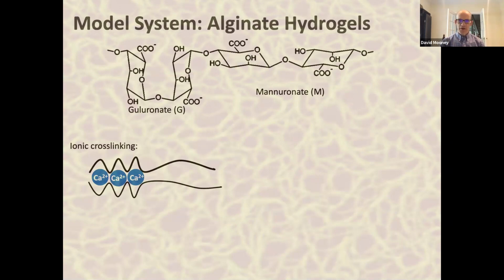Now, to explore this, the model system that I'll use in most of the data that I'll present today are hydrogels that are formed from a polysaccharide called alginate that is typically derived from seaweed. This is a block copolymer comprised of 2 different sugar units that are arranged in blocks. And for simplicity today, I'll just refer to the G blocks or the M blocks. Now, the relevance of this block structure is first that these polymers can cooperatively share divalent cations such as calcium to form a space-filling hydrogel, as shown in the schematic in the middle, but only the G blocks actually participate in this cooperative sharing of the cations, and this will be important in a minute when we talk about the structure of the networks.